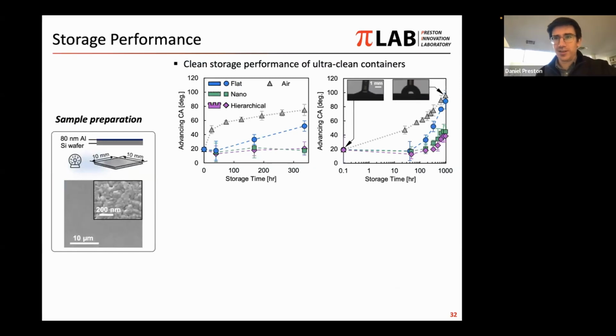Here are the results. This is the experimental side. So we have some samples here with the three roughnesses of container holding the samples, as well as a sample just stored in lab air. Lab air sample is, of course, the worst. It is an increase in contact angle over a few hours here that then continues to increase over time due to contamination. Sample stored in the clean flat container is better than lab air in blue here, but not much better. Over hundreds of hours will actually approach the lab air level of contamination.